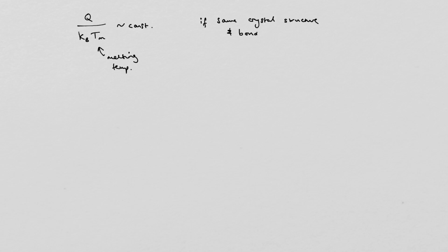Then Q over KB times the melting temperature is constant, okay? So that's the melting temperature, if same crystal structure and bonding type.